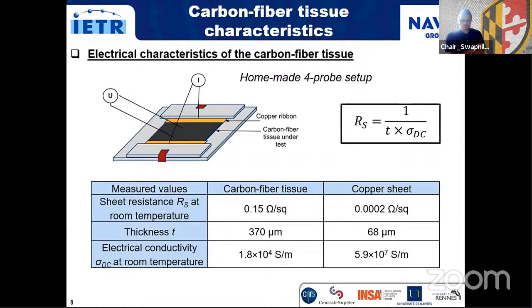Electrical conductivity of both samples was computed from the formula here, relating the sheet resistance value, the conductivity, and the sheet thickness. It is worth noting that the ohmic resistance of the radiating element is equal to the sheet resistance of the tissue due to its square shape. It is not the case of the feeding line.